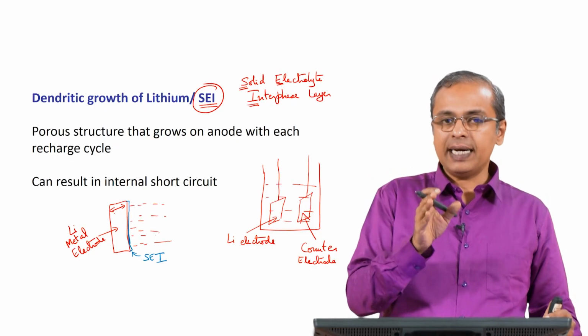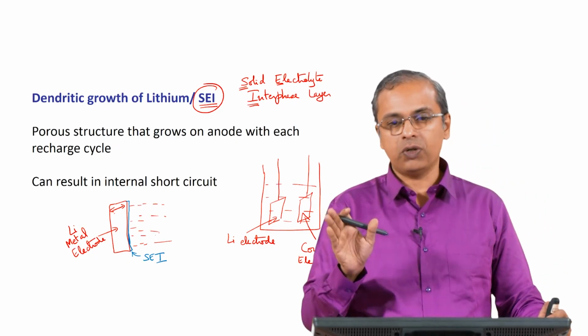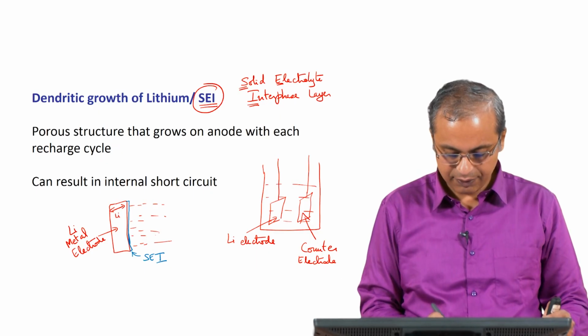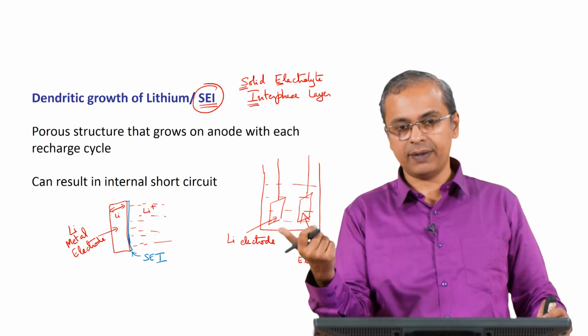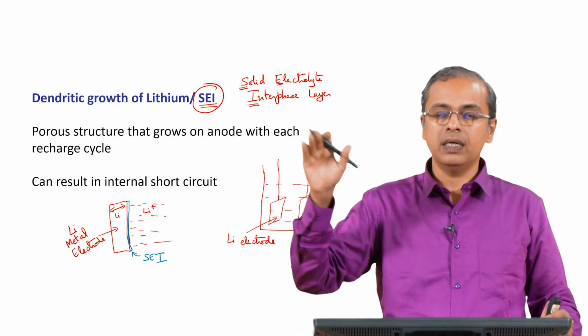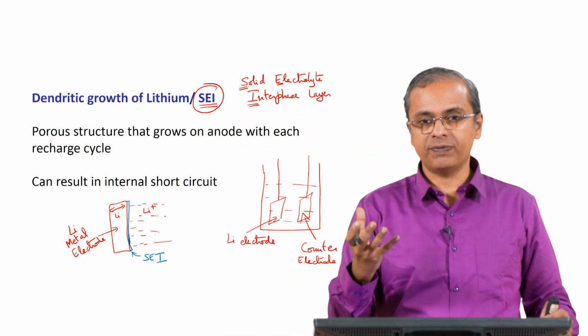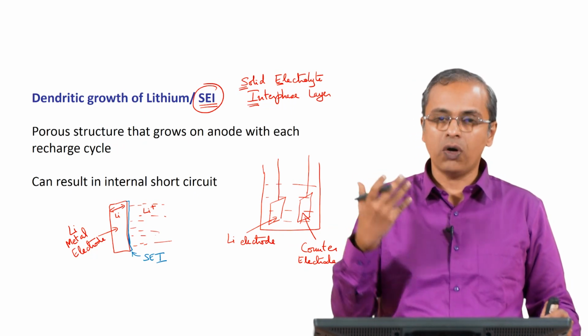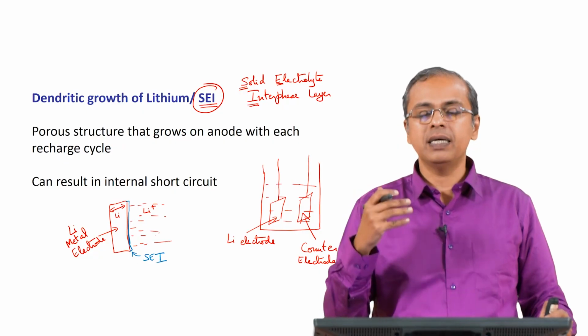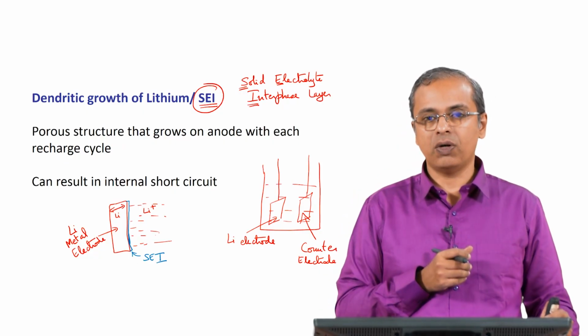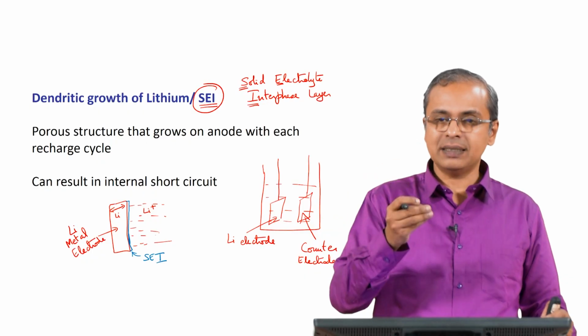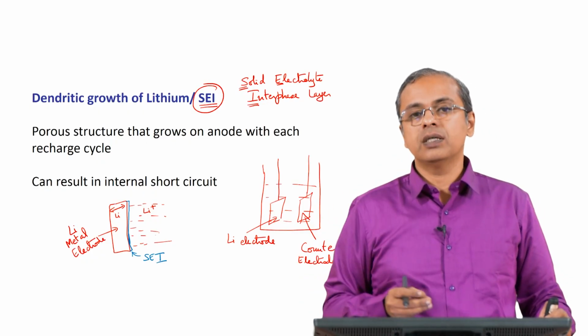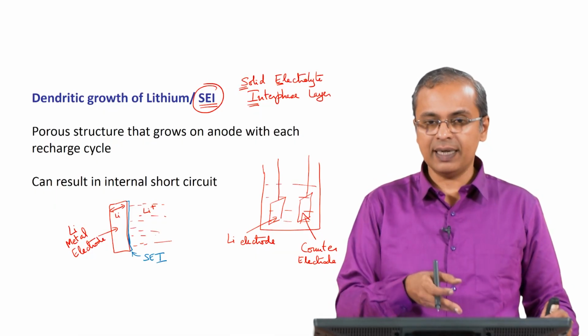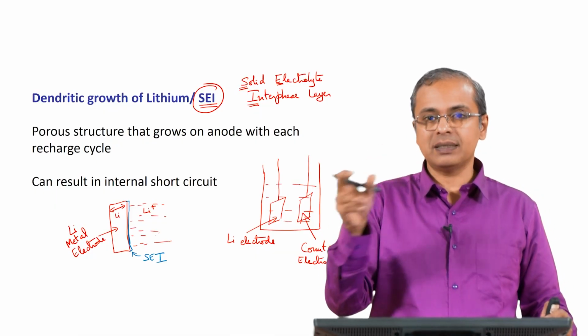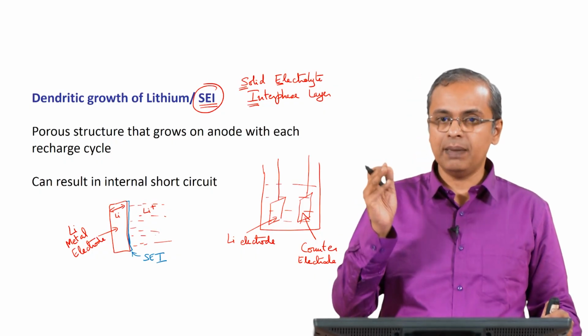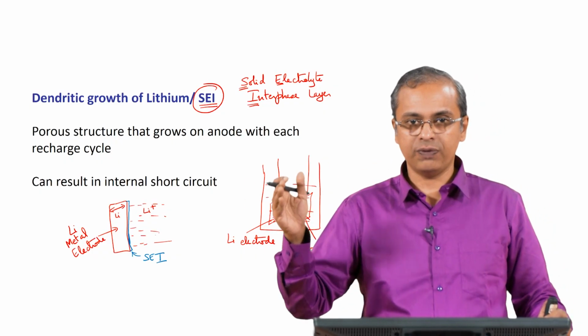But the bad thing is it now adds to the resistance for the path of the ion. So, the lithium that is sitting here, which has to become lithium plus as it goes into the electrolyte, has to pass through this layer. So, it usually adds to the impedance of the cell, which is basically obstruction to the flow of current. Impedance is a more general term, like you are used to resistance in the context of a flow of electrons, that resistance is also obstruction to the flow of electrons. You can have any species that might carry charge, in this case an ion, Li plus, is carrying the charge. So, we use a more general term, impedance, which is basically an obstruction to the flow of current.